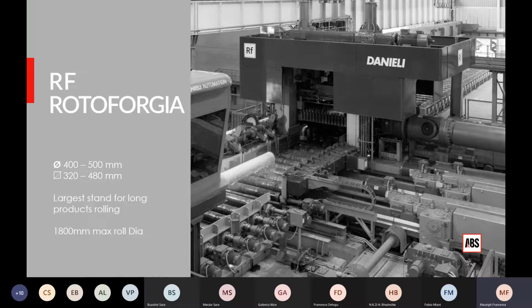This rolling stand is capable to ensure a good level of internal soundness, which makes these products not so different from typical forged products that are obtained by means of forging instead of rolling process. Thanks to the fact that a high reduction ratio, but also a high squeezing capacity, so capacity to deform the material up to the core, can be applied to the bars under rolling. Bars which can be rolled from either huge, big conti cast bloom or by ingots.